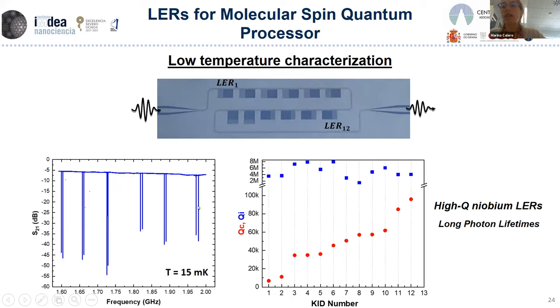Here we can see the internal quality factor and the coupling quality factor. The homogeneity and the high values of the internal quality factor represent that we have high quality niobium films. Also, we can show how we can tune the coupling quality factors, in this case, by changing the distance between the transmission line and each pixel, and also the type of coupling between the pixel and the transmission line, as we can see here.